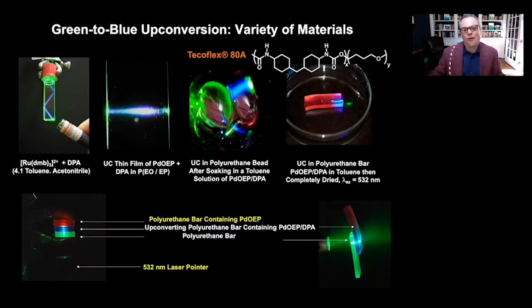And then these are all of the various materials that were involved. I won't go into all the details. Tecoflex is a medical grade approved polymer in the United States. So we sort of like that as a solid material. And again, there's the upconversion working in this solid polymer. It's simply because the glass transitions of these materials is like 100 Kelvin. So if you drop them in liquid nitrogen, you completely shut off the photochemical upconversion process. But anyway, we managed to go through all of these different materials.